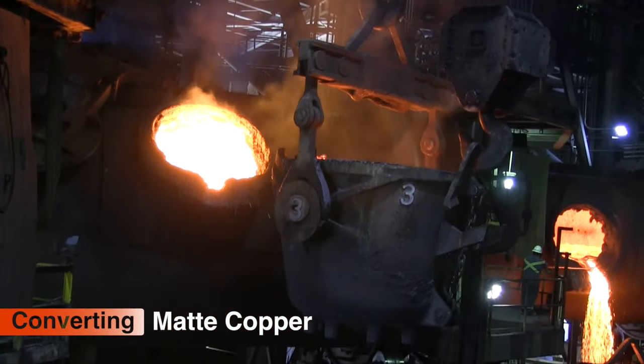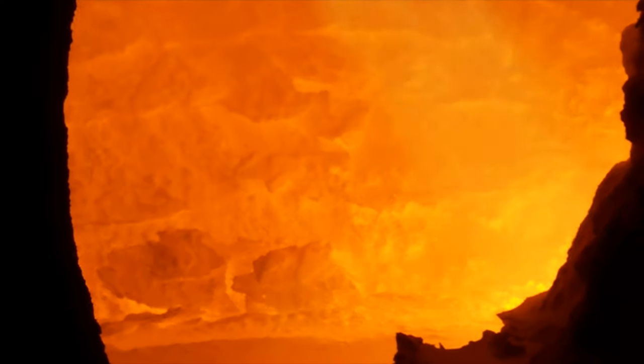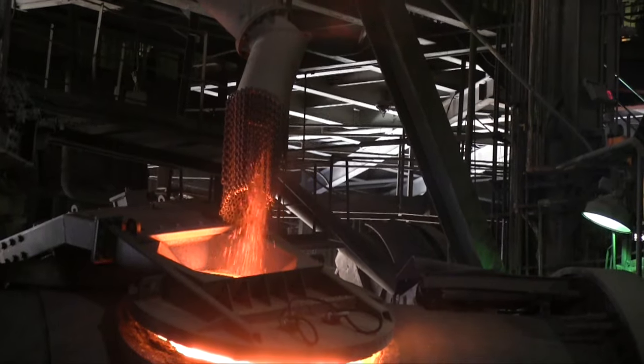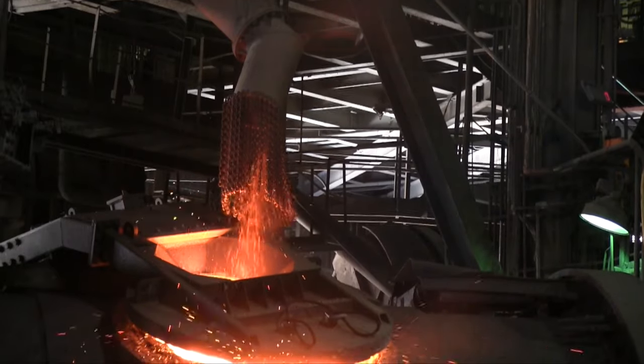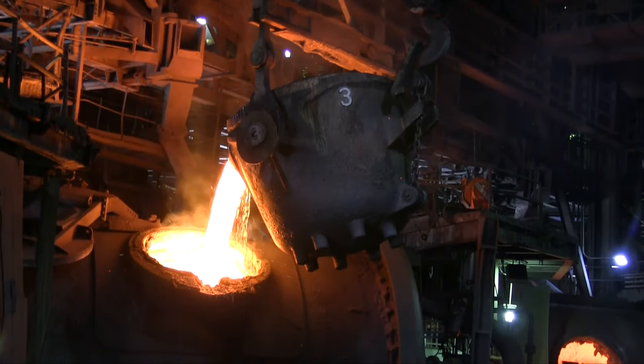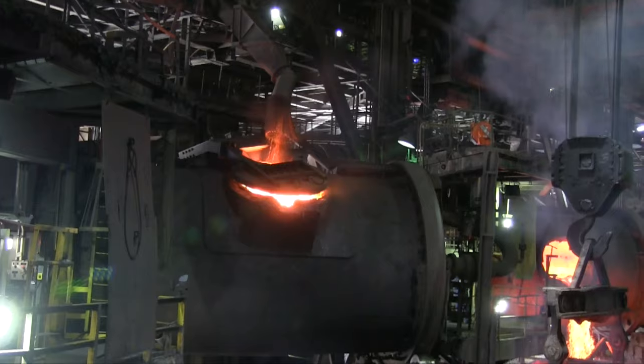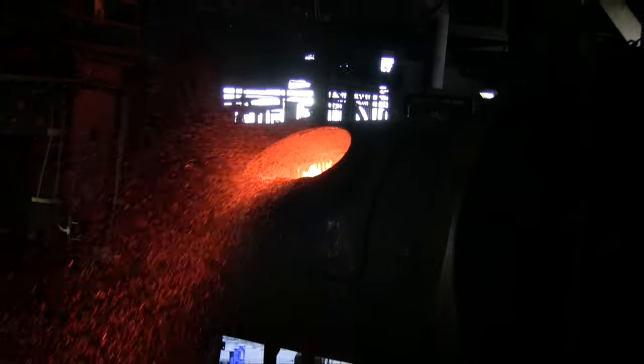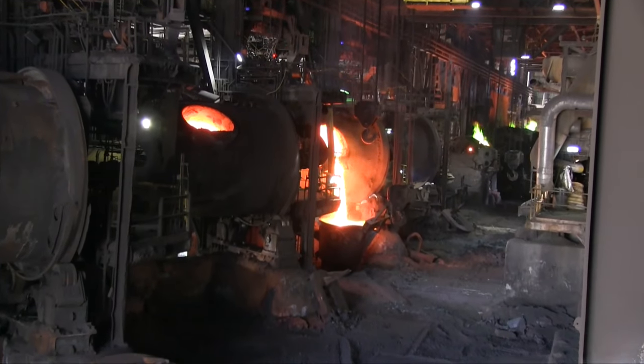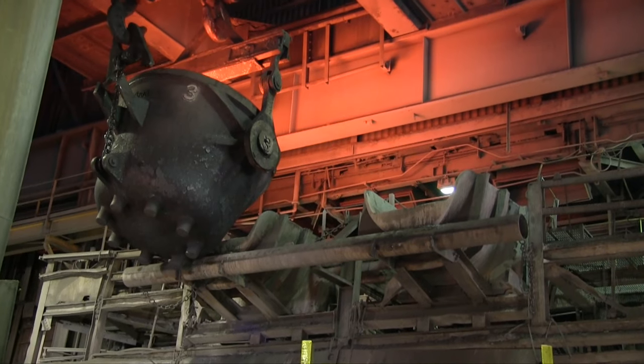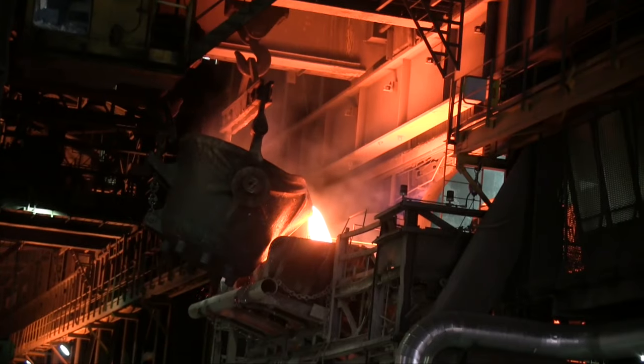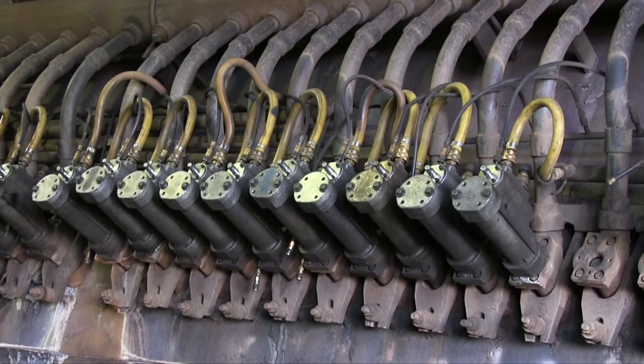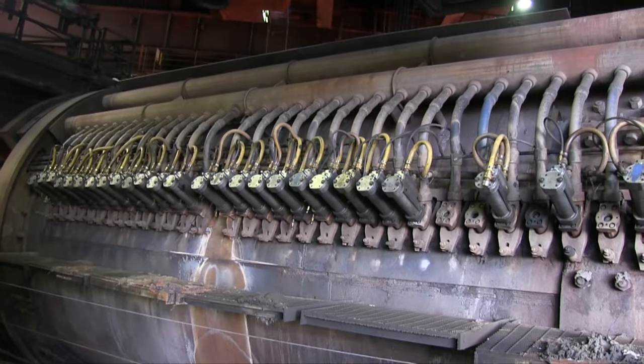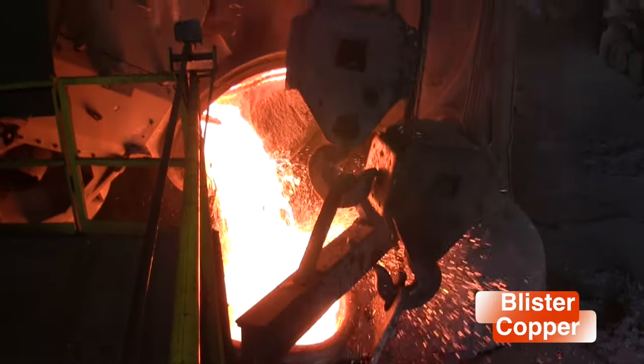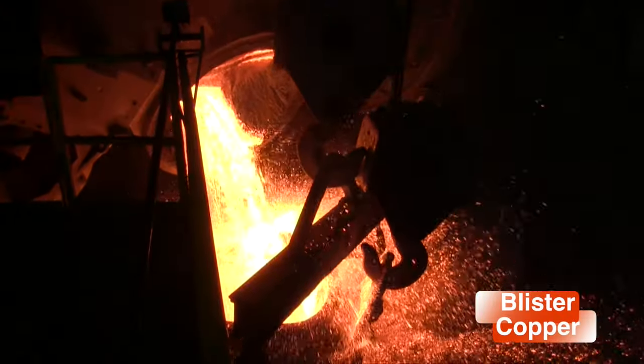Converters remove iron and sulfur using high-volume blast air and more added silica flux to separate the iron as slag. We mix matte from the electric furnace with silica flux and blow blast air into the molten matte to oxidize the iron sulfide, creating an iron silica-based slag, which we transfer back to the electric furnace to recover additional copper. Blowing more blast air into the converters oxidizes most of the remaining sulfur to form impure blister copper.